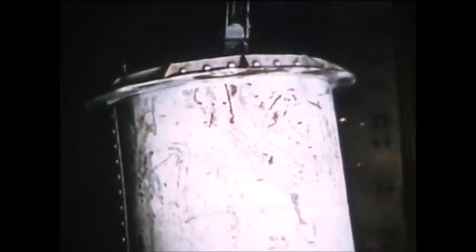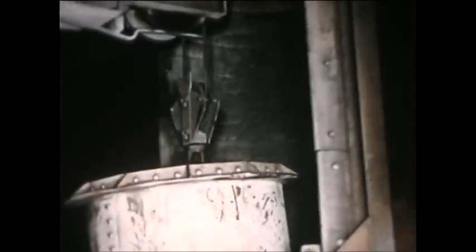The charge consists of quantities of iron, pig iron and steel, carefully measured by weighing and dropped into a charging bucket. On top of this material is placed a layer of coke with limestone and a small quantity of ferroalloys to maintain the specified analysis. Now the bucket goes to feed the fires of the cupola and produce the liquid metal.